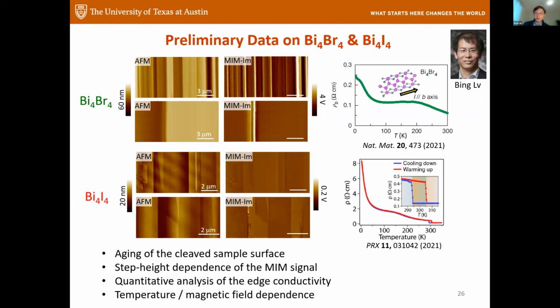So we just exfoliate and measure immediately, and we do see some time dependence. Your bismuth is just right at the boundary of the phase transition. Yeah, that's right, you are exactly right. It's a fairly easy experiment: we just heat up to, I don't know, 40 degrees Celsius. It's a direct test whether we recover these bright lines in the iodine sample.